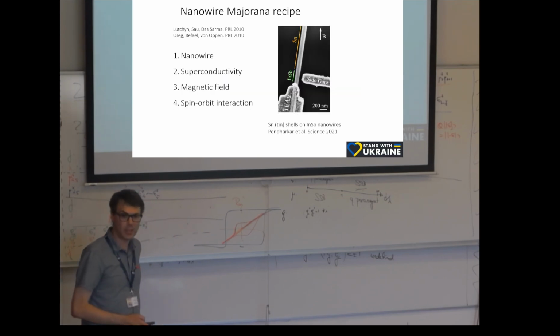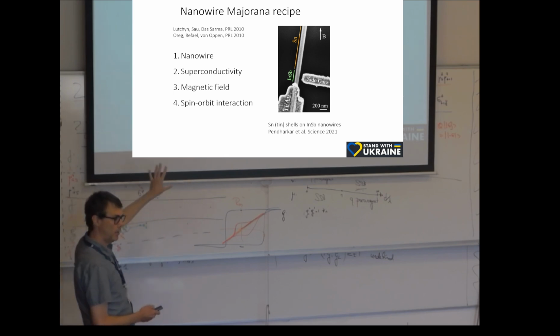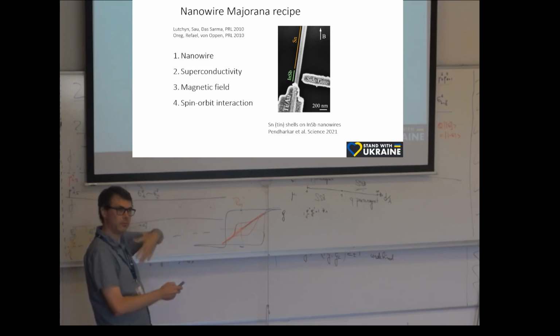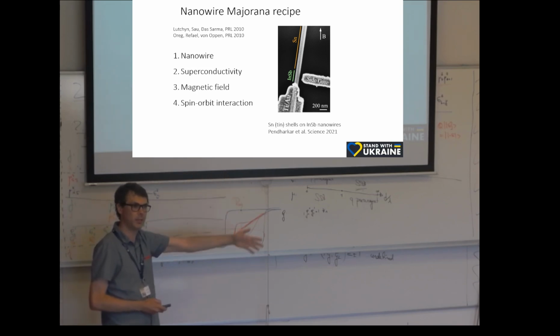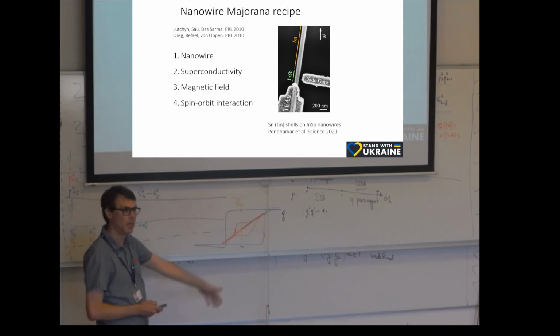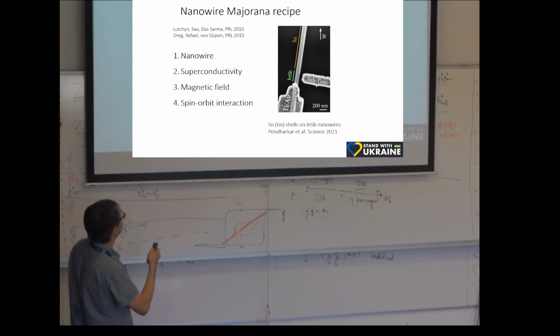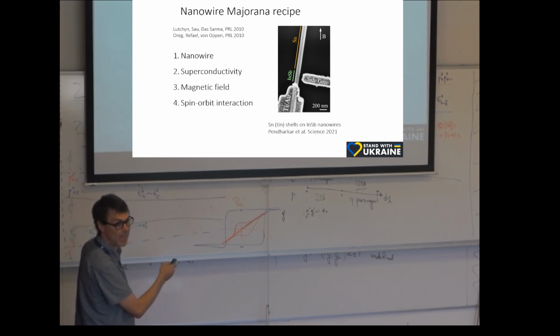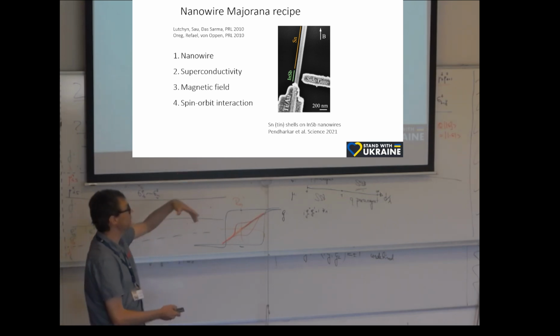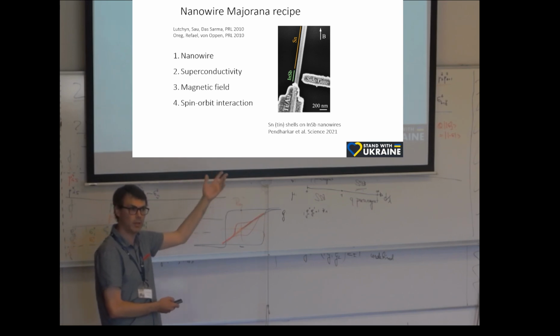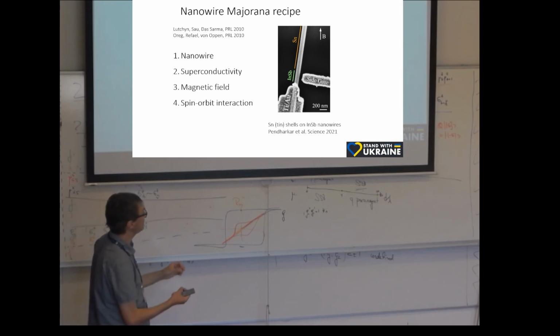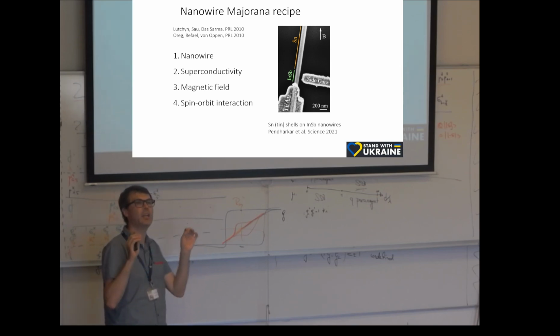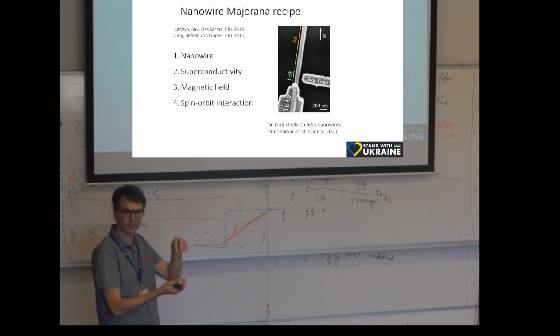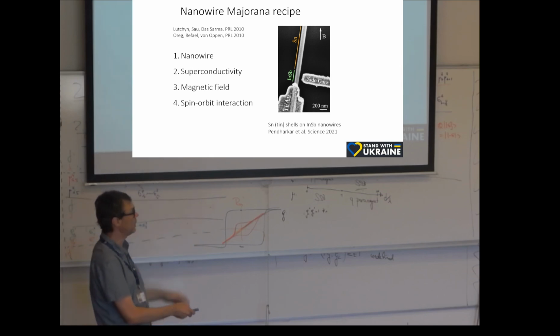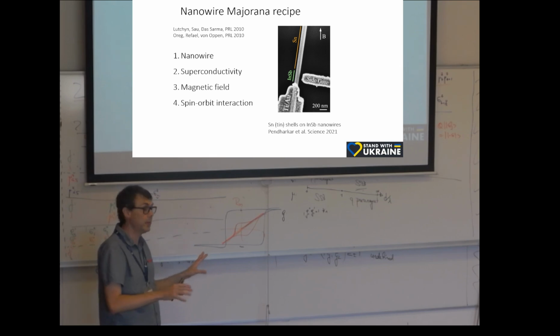Now, still on this topic, I just want to highlight that the recipe to make this Majorana, with all these properties, non-abelian for qubits and for fundamental physics, a particle that is its own antiparticle, is relatively straightforward. In 2010, I was already working with these kinds of nanowires. It's about a 100 nanometer diameter rod of semiconductor. In this case, indium antimonide; indium arsenide was tried as well, germanium, other things. And it's already such a high quality object. It's a single crystal, right? So no crystalline defects in this whole nanowire. It could be microns long, so the crystal growth here is amazing.